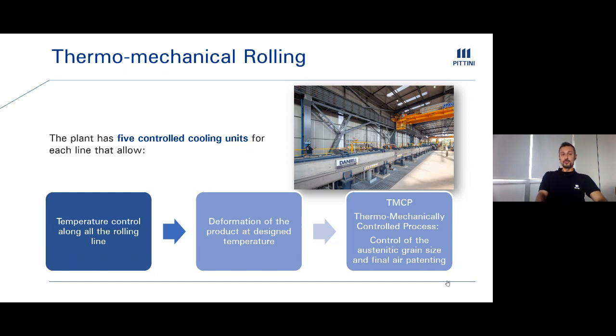For this, it might be useful to give a little background here. So for that, we need to consider the microstructure of the steel, and to consider that the microstructure is formed by austenitic grains. Well, the thermomechanically controlled process allows us to get a smaller austenitic grain size during rolling and keep it until the cooling conveyor. This feature is one of the main aspects behind the final product properties enhancement related to the thermomechanical control process.